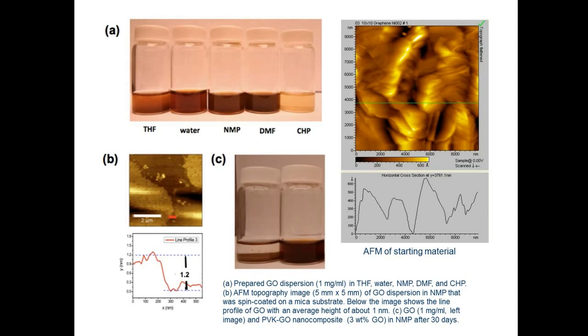On the AFM image, you can see the analysis we've done on a single sheet with a thickness of about 1.2 nanometers, indicating that we indeed get an almost monolayer, if not bilayer, derivative of the graphene. The AFM image on the right shows non-exfoliated native graphite starting material, where you can see the lamellar sheets stacked up on the native graphite.